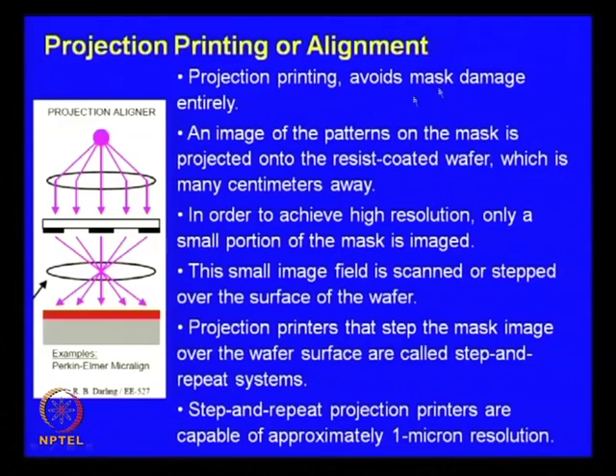Well, it completely eliminates mask damage, but that is not the only thing. The issue is that here you keep a substantial separation distance; the mask and the film are nowhere even close to contact, and there is an additional condenser lens between the two. So, an image of the patterns on the mask is projected onto the resist coated wafer, which is a few centimeters away. In order to achieve high resolution, only a small portion of the mask is imaged. Of course, if you have a wide area, then the condenser lens will fail. This small image field is scanned or stepped over the surface of the wafer.